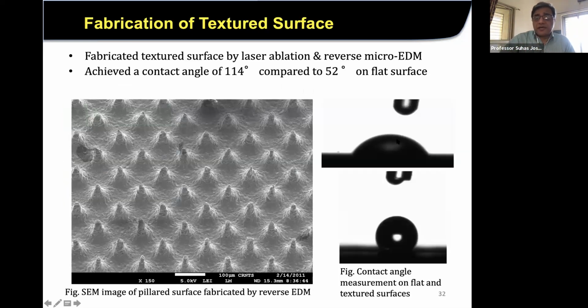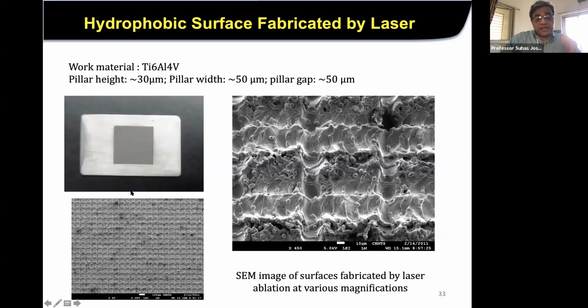Of course, we did contact angle measurement here. On a flat surface, the droplet spreads and is flat, whereas on this surface, you find that the droplet is sitting. It has a much higher contact angle, about 114 degrees compared to 52 on the flat surface.